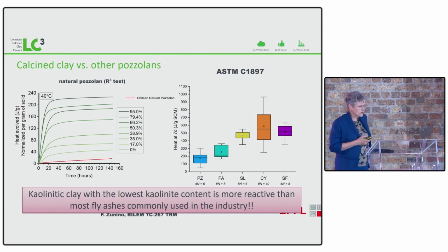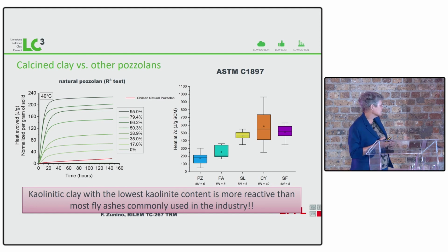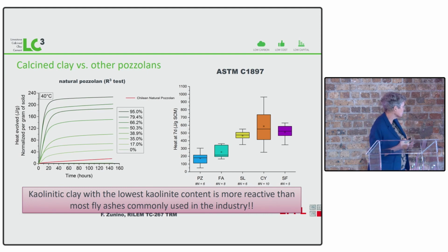And you can look at the reactivity of these different SCMs. We spent a lot of time developing this, what's now a standard ASTM C1897, where we can compare the different reactivity of different SCMs. And you can see the clays, which are in orange here, are very comparable with slag and with silica fume, but of course the amount of silica fume we've got available is really minuscule. And these three, slag, calcined clay, and silica fume, are much, much more reactive than fly ash or natural pozzolans. And the fact they're more reactive will mean you can go to higher levels of substitution, and higher levels of substitution means you can save more CO2.